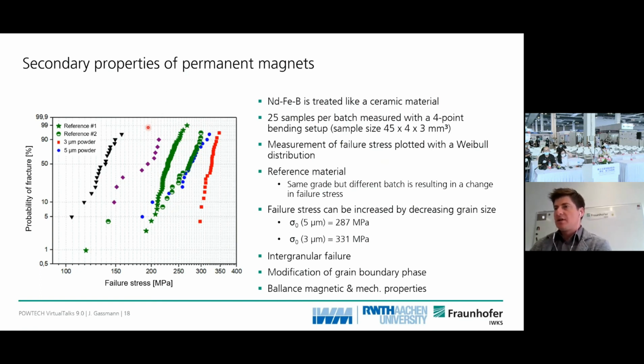With the material we produced in the project, we could reproduce this commercially used material, and with decreasing particle size, the failure stress could also be increased by about 50 megapascal. So the take-home message is, of course, that with the powder metallurgical process, the mechanical properties of sintered magnets can be tuned. One always has a balance between mechanical properties and magnetic properties, but we think that secondary properties like the mechanics are also very important for applications. We saw that when the material failed, it was an intergranular failure, and with further modification of the grain boundary phase, the properties could be further improved.